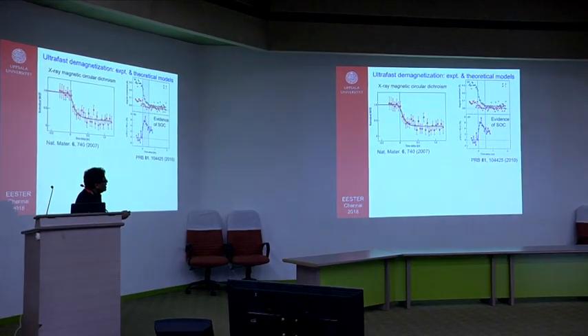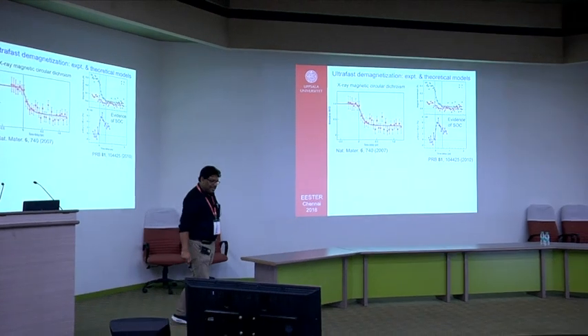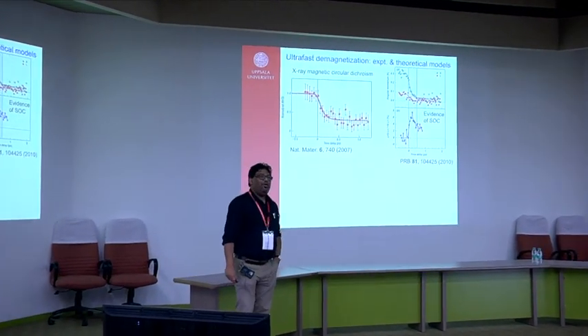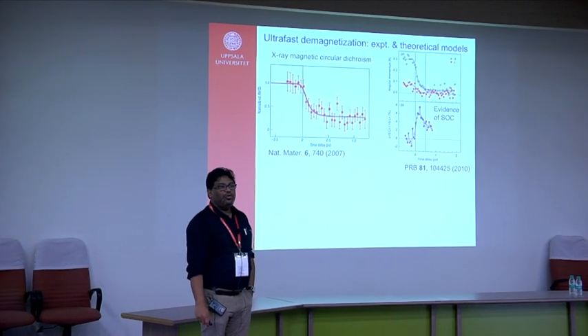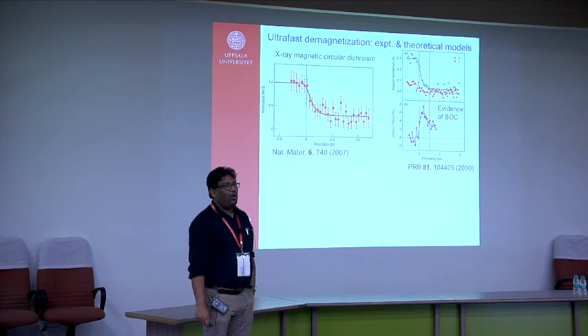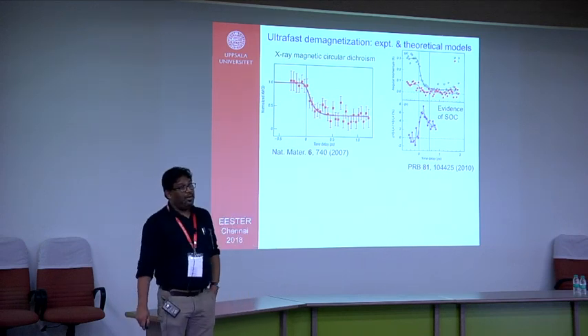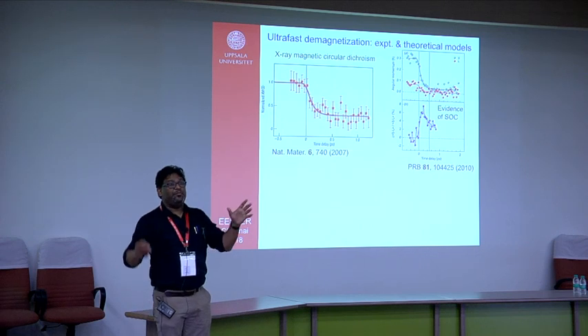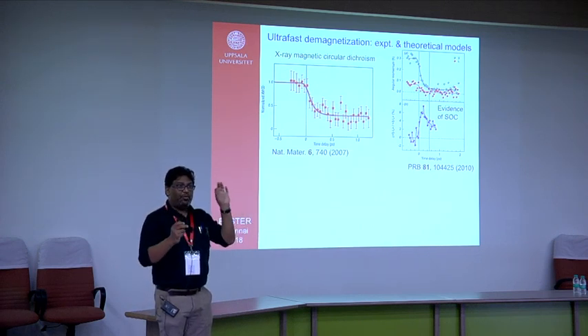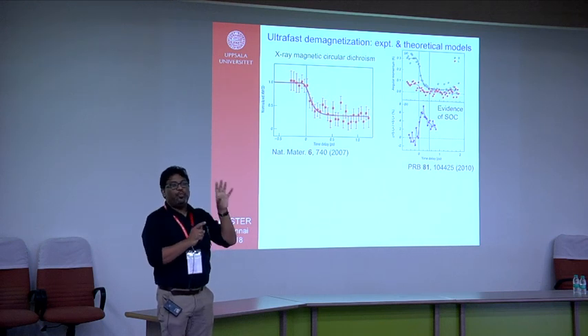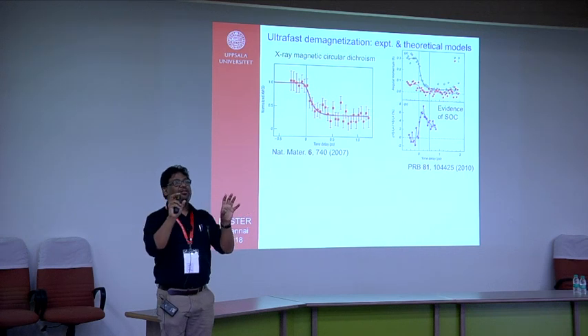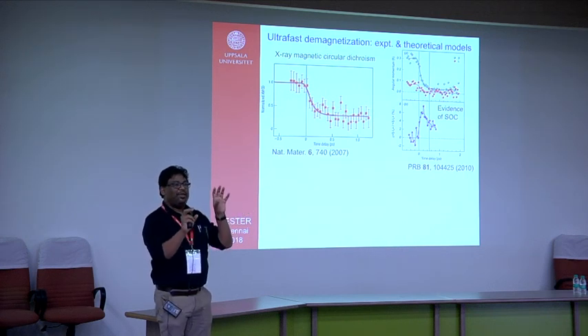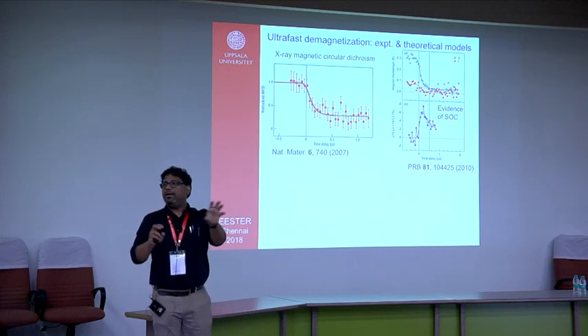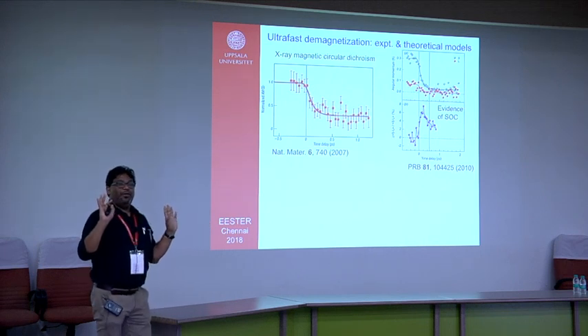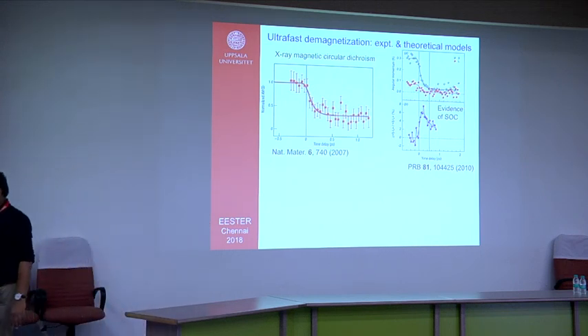So this is like this. The interesting thing of doing an XMCD measurement is that you can get access to the spin moment and orbital moment. I don't know about any other experimental technique by which you can get the orbital moment. So this is a very powerful measurement, element specific. That means if you have several components in your system, you can selectively choose your photon energy to probe each of the elements separately. And you get information which is completely element specific. That means spin and orbital moments of iron, cobalt, nickel, separately. Extremely powerful technique. But you have to go to a synchrotron center to do this experiment.